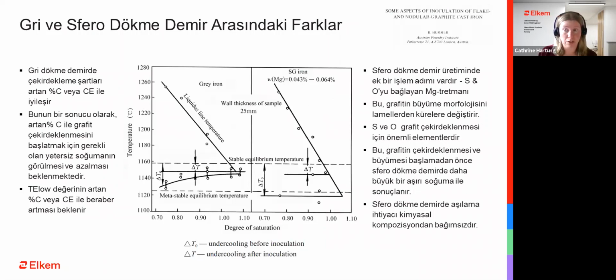And then to the difference between gray and ductile iron. Now in gray iron, the nucleation condition improves with increasing carbon and carbon equivalent. You can say that gray iron is actually a self-inoculating material, or the inoculation condition improves with increasing carbon and carbon equivalent. This is represented here on the curve to the left, where you have a representation of the liquidus temperature, which is the line that crosses and down to the stable eutectic temperature. And then you have the delta T, which is the undercooling after inoculation, and delta T0 is the undercooling needed before you inoculate. And as you see, the undercooling before inoculation in gray iron improves with improving carbon equivalent.